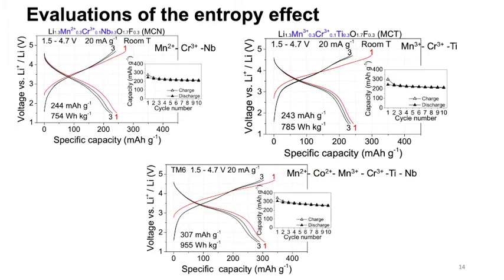And a similar proof has also been done to demonstrate that chromium itself does not account for the improved capacity from TM4 to TM6. This is achieved by comparing the TM6 compound with two chromium-containing TM3 compounds at the same chromium concentration. And by these 3 groups of comparison, we can strictly prove that it is the overall entropy effect, rather than the incorporation of a specific transition metal species, that leads to the improved electrochemical performance.